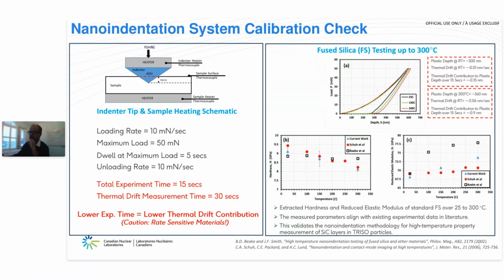On the top left, what you see is the schematic of our system, where we use 2 independent heaters to heat the specimen, in this case fused silica, a sample provided by Micromaterials, and then the indenter tip itself. We do use a secondary thermocouple on the top of the sample near the edge, not exactly where we indent, just to minimize the temperature gradient between the indenter tip and the sample surface.